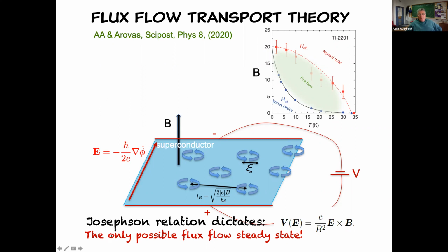And it is really the only possible flux flow steady state that you can have, one in which the current doesn't increase linearly in time, is the one where the vortices on average move exactly with this E cross B divided by B squared velocity. So the reason I'm posting this picture of the flux flow, which is quite different from the one you see in the 10 to the 4 paper we saw before, is that I'm looking at the response to an electric field rather than to a current. And by that, I'm avoiding all the difficulties that people have run into trying to write down equations of motion for vortices to predict what is going to be their velocity as a function of current, let's say. Here, the velocity is completely dictated. There are no parameters that are related to the material properties of the superconductor. It's a pure relation, nearly a tautology, that the velocity of the vortices is precisely dictated by B and E alone. And of course, the velocity of light.